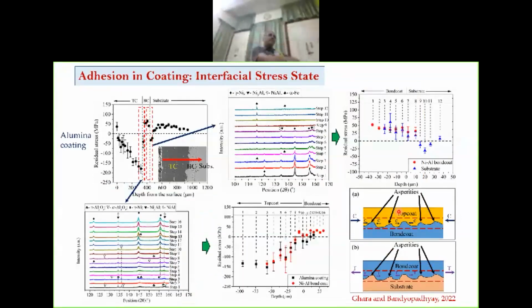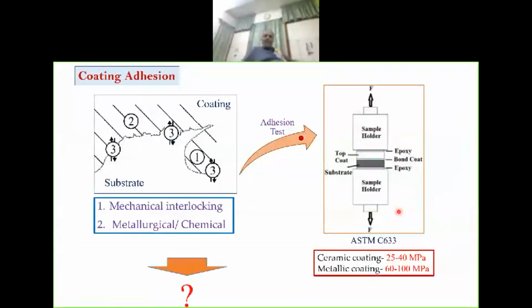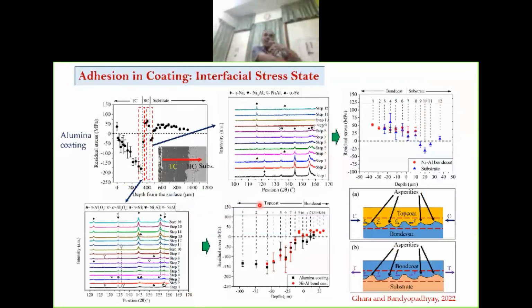This is an example. Okay. Before that, there are several possibilities of the bonding. It can be mechanical interlocking at the rough surface. We make the substrate rough initially by grit blasting, or the bond coat, if you spray on the grit blasted surface, has a rough surface. Or it can be metallurgical chemical bonding. We don't know. This investigation is published. One can find it.